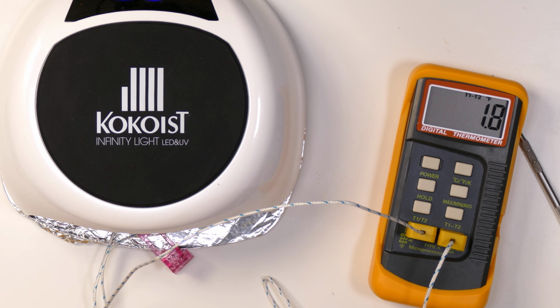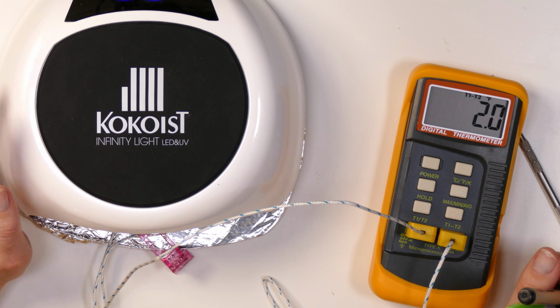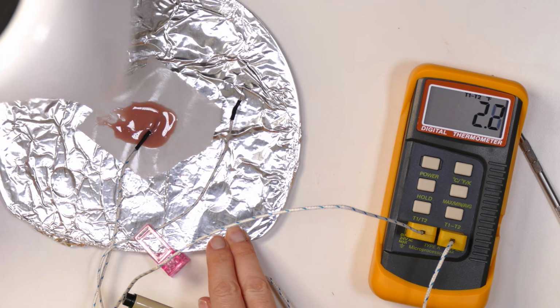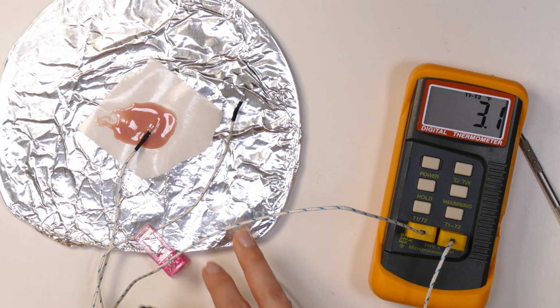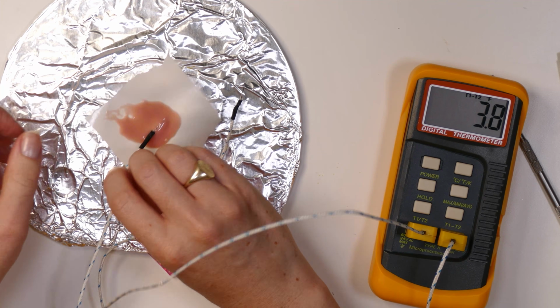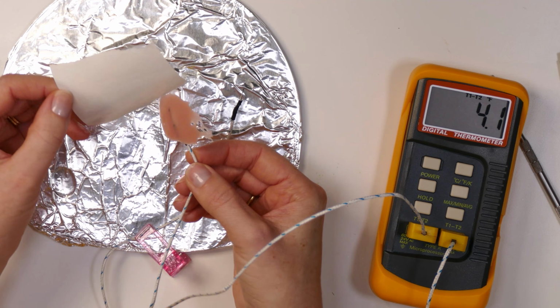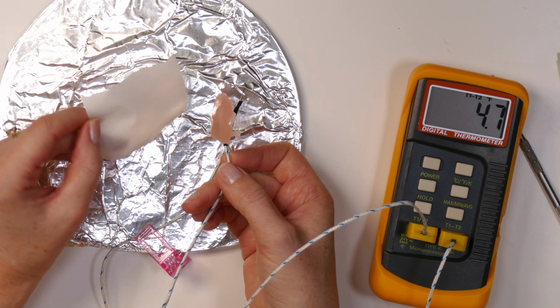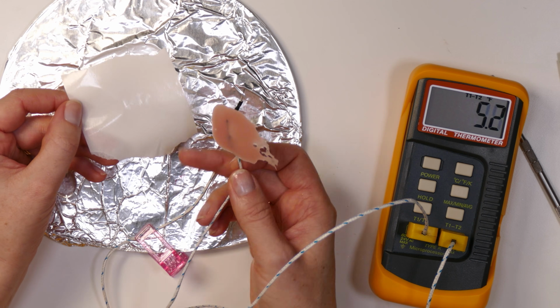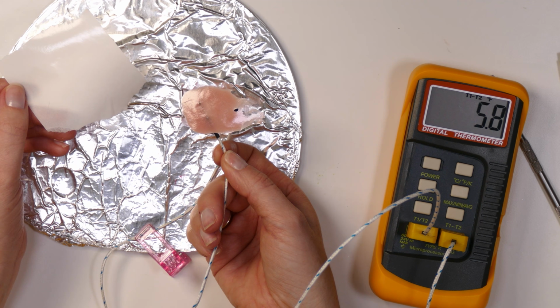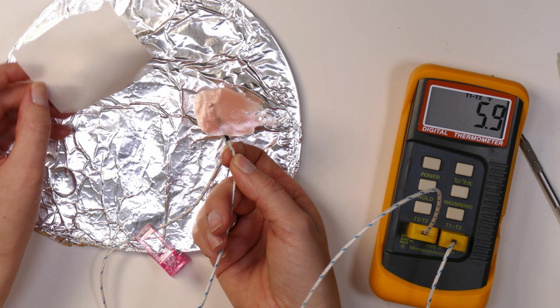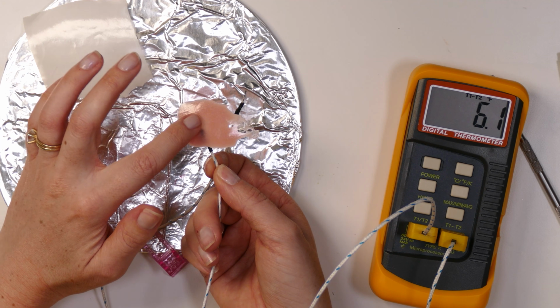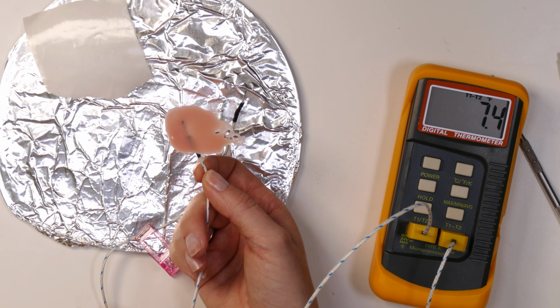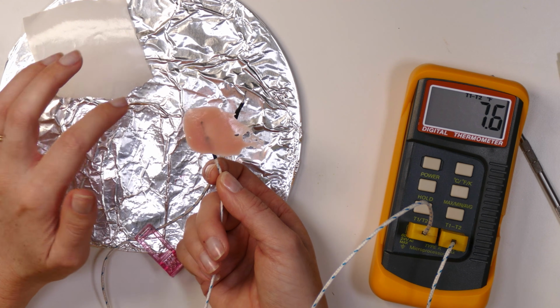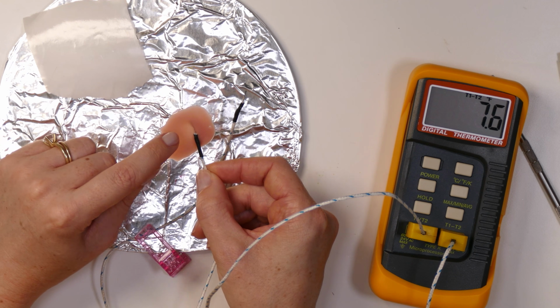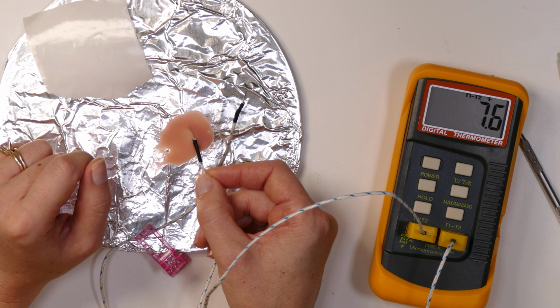So this information is really important to us now that we completed this. I'm going to take this out of here so you can see. Okay. So again, we can do a visual check on this. You can see that the gel came off totally clean. There's no wet residue on the actual form paper, which tells me that the gel cured all the way through to the bottom. You can even see that it's dry to the touch on the bottom since there was no exposure to oxygen. On the bottom side, it's not even going to be sticky. And you can see that my little sensor is in there, stuck in the gel.